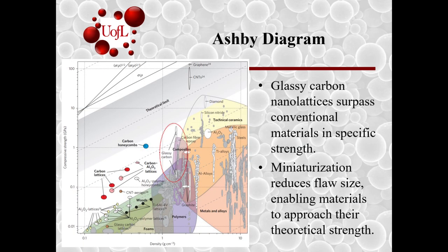The Ashby diagram plots the compressive strength versus density for various carbon-based materials, including bulk glassy carbon, glassy carbon lattices, alumina-coated carbon lattices, and carbon honeycombs. Overall, bulk glassy carbon showed lower strength due to larger internal flaws, while glassy carbon lattices showed lower density but competitive strength to density ratios due to their nanoscale architecture, while the alumina-coated carbon lattices showed higher compressive strengths due to the alumina stiffening effect, and then honeycomb structures achieved the highest performance due to their topology. The diagram also shows the extreme nature of miniaturization and the structural optimization that shifts glassy carbon towards its theoretical strength limit by reducing the flaw sizes and enhancing the load distribution.